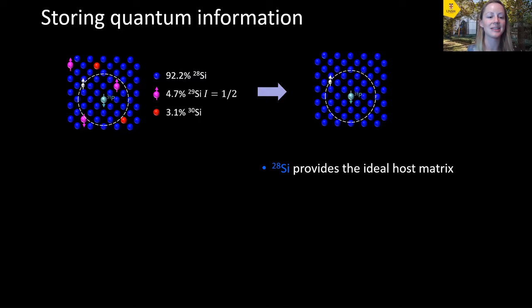So in order for this to be the case, we need to switch to using isotopically purified silicon, because if you just harvested natural silicon, it comes in the following isotopic abundance shown here, where you've got three isotopes in the relative fractions. And silicon 28 and silicon 30 are both our friends because they don't contain a nuclear spin. Whereas the silicon 29 nucleus, which occurs in abundance of around 5% in natural silicon, has a nuclear spin of 1/2. And this means it has a magnetic moment.